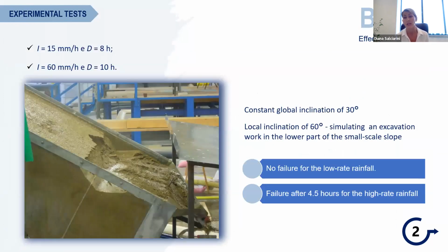As for the results of the second group of tests, in this case, we kept constant the artificial slope inclination at the maximum value equal to 30 degrees. And we realized a local inclination of 60 degrees, simulating an excavation work in the lower part of the artificial slope. We tested 2 patterns of rainfall. The first one is a low rate rainfall with an intensity equal to 15 millimeters per hour. And the second one is a high rate rainfall with 60 millimeters per hour.